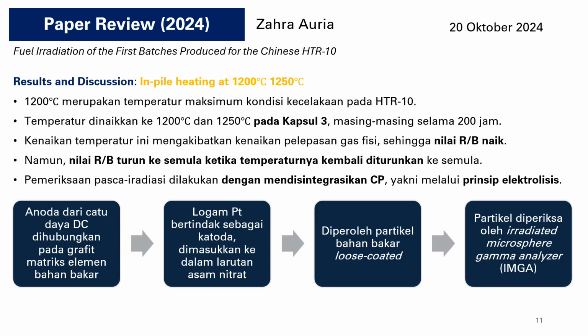To the results and discussion for in-pile heating at 1200 degrees Celsius and 1250 degrees Celsius. So 1200 degrees Celsius is the maximum temperature for the accident condition at HTR-10. For capsule 3, we raised the temperature to 1200 and 1250 degrees Celsius for 200 hours each. This increase in temperature would cause the gaseous fission product release to increase, as well as the R/B value. But the R/B value would go back to normal once the temperature was back to normal.